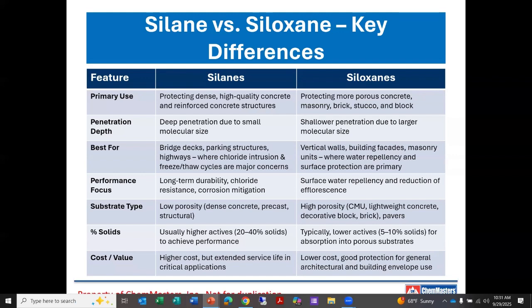Applications, which are these products best for? Silanes, bridge decks, parking structures, highways. And these are areas where, of course, they are very dense concrete design, mixed designs and finishes. And there are also applications where you might be more concerned about chloride intrusion and freeze-thaw cycles because of the nature of the environment that they're in. Siloxanes may be best for vertical walls, building facades, masonry units, where the key is really water repellency and good surface protection. Performance focus, silanes, long-term durability, chloride resistance, corrosion mitigation, siloxane, surface water repellency, and reduction of efflorescence.